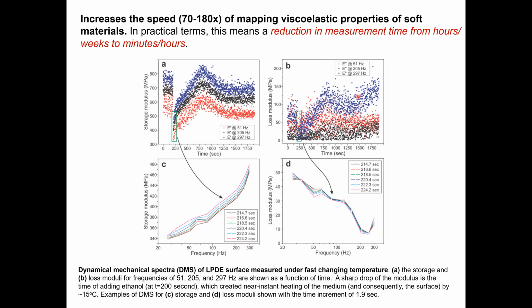The loss modulus is a bit noisy in this case, because it is pretty small compared to the storage modulus. Technically, if this is a problem, it is possible to improve it even further. But again, there is no averaging here. It's literally raw measurements. If you do averaging, you can clearly see a change starting from the softest part. This is going through 0.7 seconds. So it's pretty fast, scanning can see the change of mechanical properties. After averaging the loss modulus, there's somewhat different behavior, but at least it is definitely there.